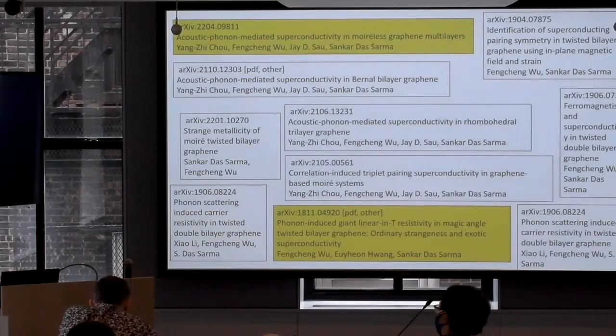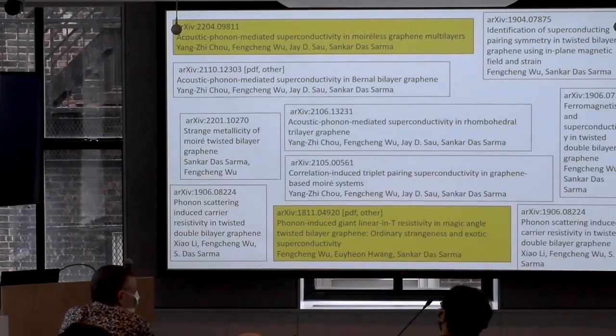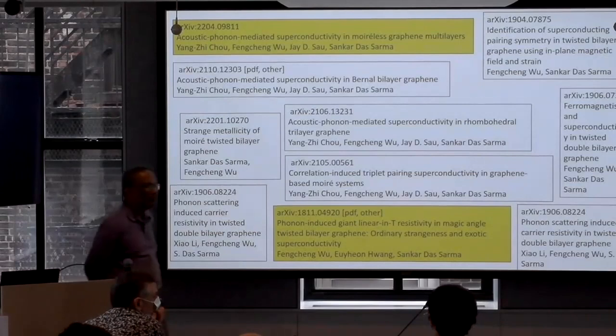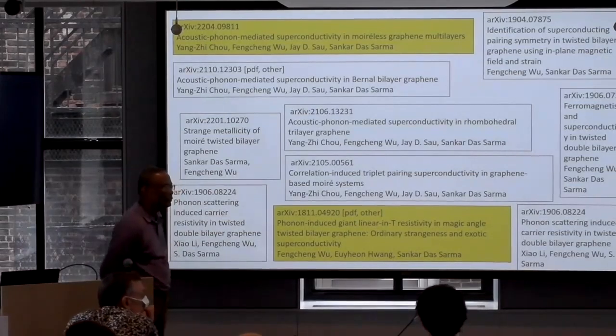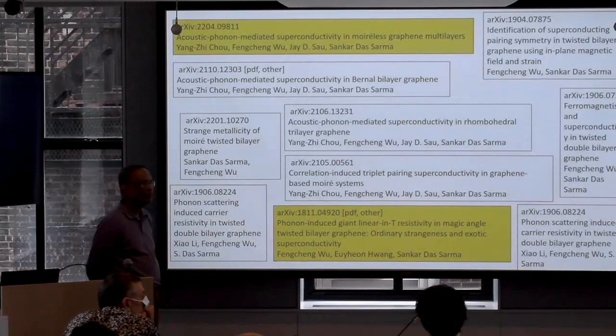Electron-phonon interaction has not been ruled out as decisive there for resistivity. That's all I'm saying. May I make a point about perhaps purity of samples? If you look at the theoretical calculations, every linear resistivity, everything that gives you a linear regime, if you just extrapolate that to zero temperature, you get a strongly negative intercept. Yes. And every measurement in both graphene and correlated materials does not have that negative intercept. Correct. The question is, is that simply a disorder offset that's pushing things up, or is there something else?